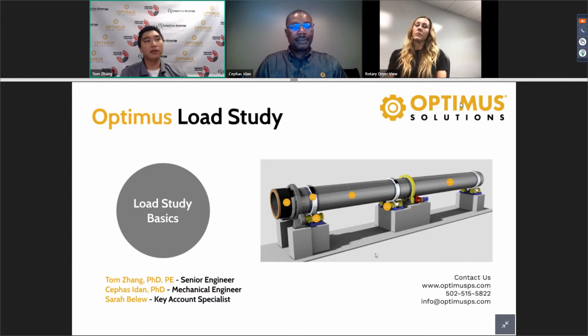That's a pretty big difference, especially on a dryer, because on the kiln, the saving grace is the heavy spot is actually the refractory. And the kiln has got a little bit less production than a dryer. 8 foot by 30, 8 foot by 40, 50, you could do, say on the asphalt side, I know we could do 200 tons per hour, frac sand in the 200, 180, 150 tons per hour. You change that by about 50%. That's another 50 to 100 tons you just added in there. So that matters.